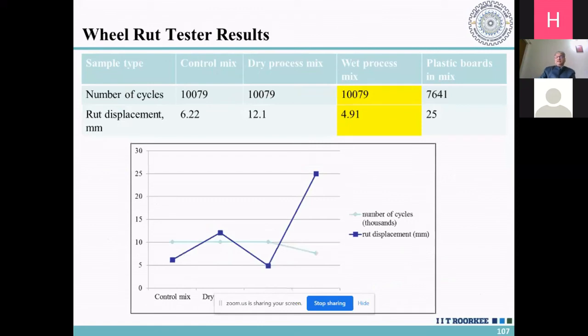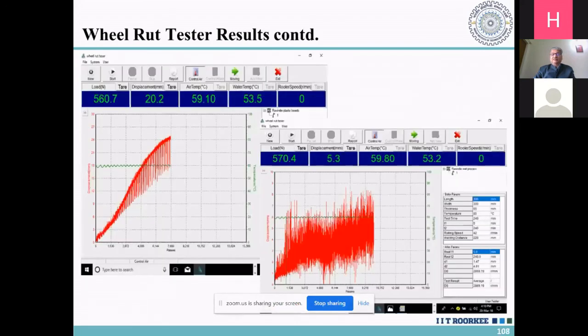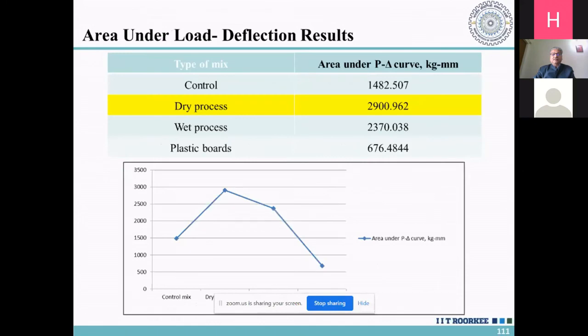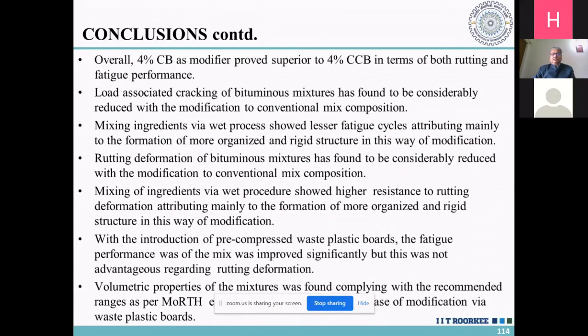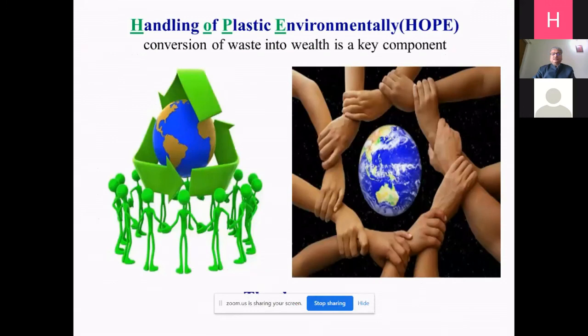And wheel rut tester is the condition when we simulate the conditions of the rutting in the lab. It is the wheel which passes to and fro over the sample, and after 1000 passes, after 2000 passes, after 1 lakh passes, we try to find out what is the rut depth, and it should be less than 25 mm of the sample. So this is about what I wanted to show you.